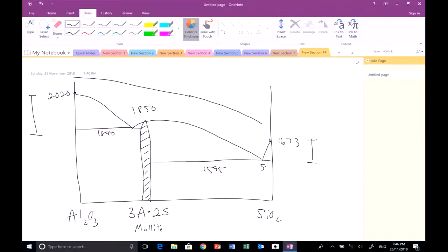So the conclusion from this is actually that alumina is a very powerful flux for silica because of the steepness of that liquidus surface. So a little bit of alumina has a big effect on silica, but a little bit of silica on alumina doesn't have that big effect. Even though if you stretch it all out, you'd say, yeah, it's bigger. But on a percentage-wise basis, just look at the slopes of the liquidus surfaces. And you can see that actually alumina is a more powerful flux than silica at low levels.